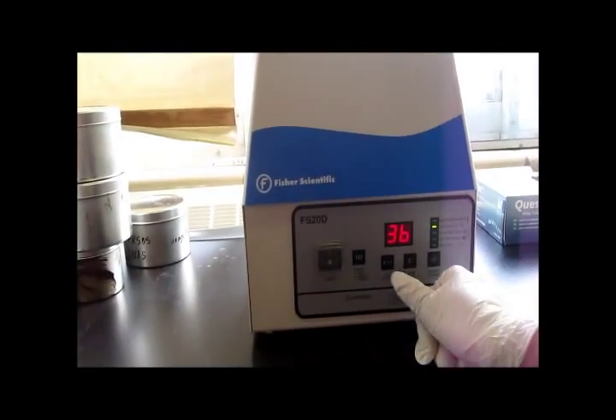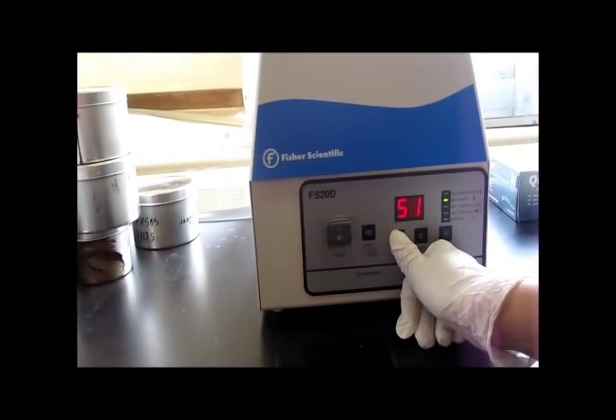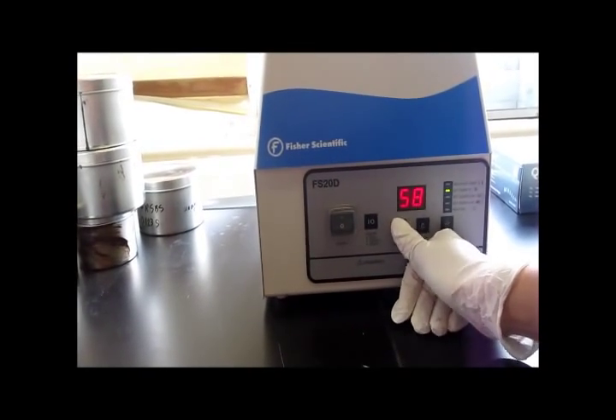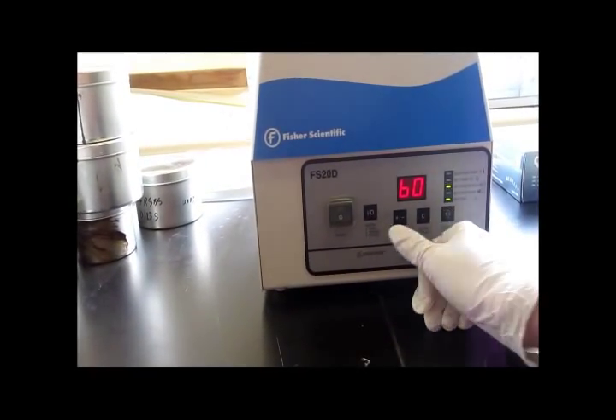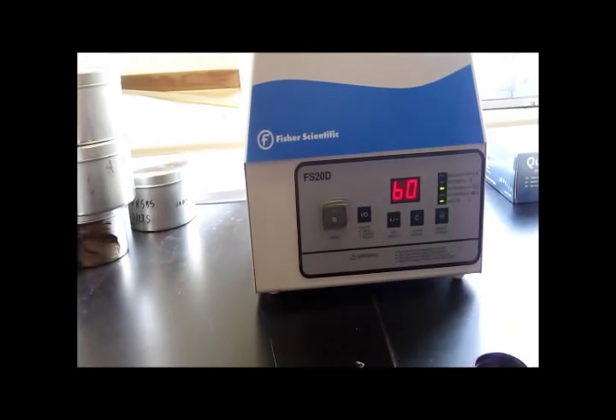Substrates are submerged for 60 minutes at 60 degrees Celsius to remove any residue from the cutting process and neutralize the surface of aggregate to its original condition.